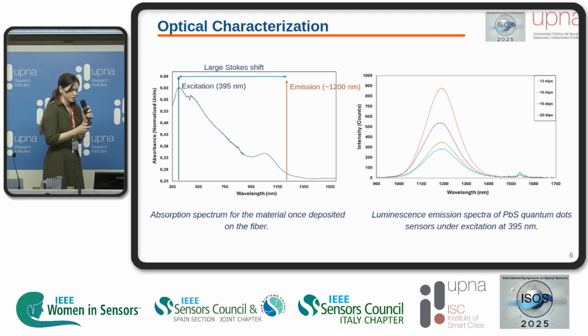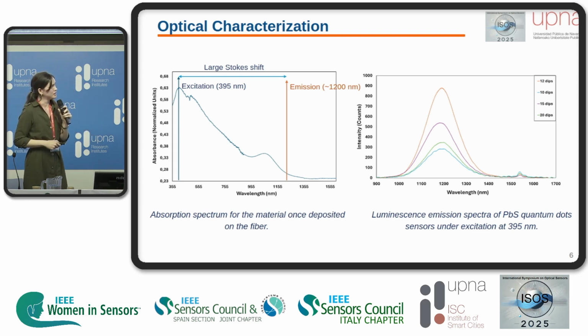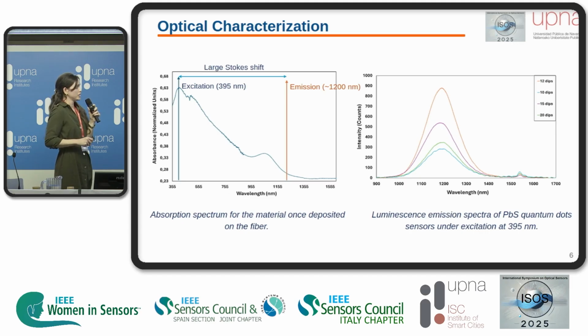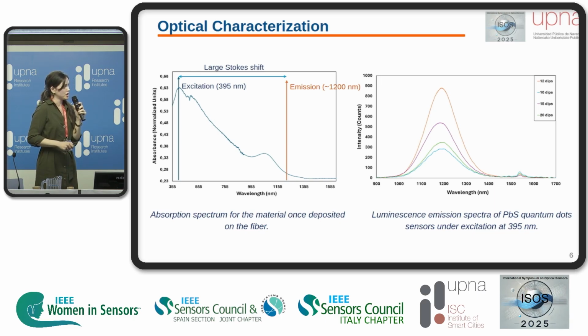After deposition, we measure the absorption spectra, and we can observe a broad band from the ultraviolet to the visible range and the maximum around 1,100 nanometers. This response allows us to excite the quantum dots with a 395 nanometers LED, and we can observe that the emission is around 1,200 nanometers. This large Stokes shift allows us to avoid self-absorption and signal overlaps, which is another of the main problems for luminescent sensors.